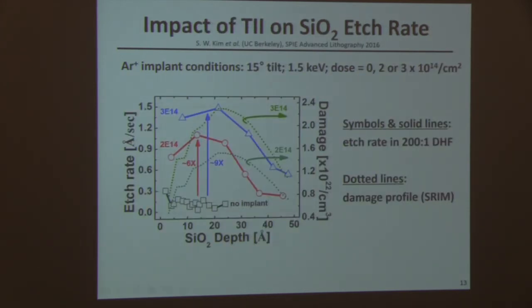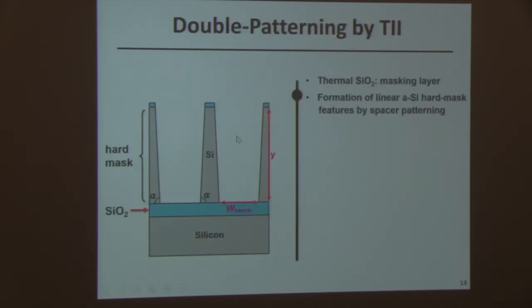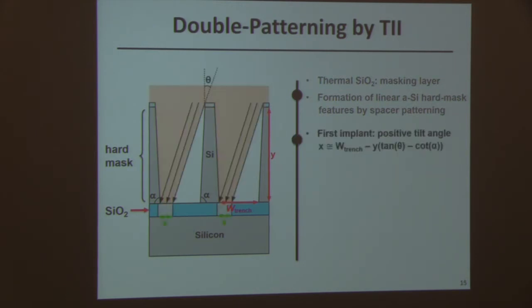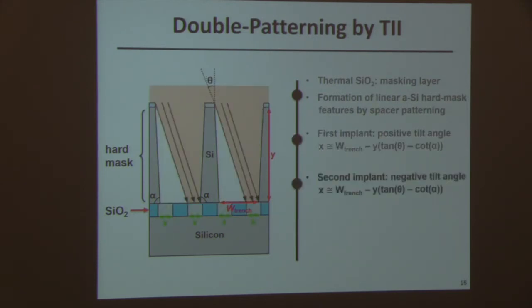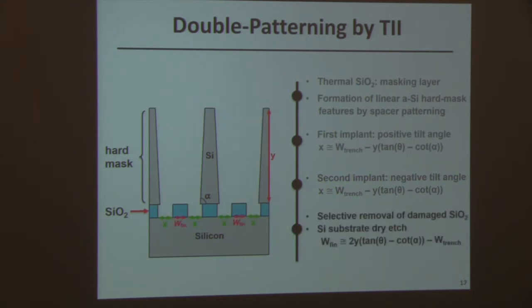The key is that we did some experiments looking at the etch rate of that hard mask, silicon dioxide, as a function of depth. Without an implant, the etch rate in hydrofluoric acid is very low. But with implants, depending on the dose, you can enhance the etch rate quite a bit, by almost 10 times. So the idea here is, let's say you have some pre-existing features on the mask, and you want to double the density on the surface of the wafer. These are just straight lines shown in cross-section. You can do a tilted implant to achieve sublithographic damage regions, and then a second implant at the opposite tilt. Then you can selectively, more quickly etch away the damaged regions, and you end up with twice as many trench features as before.